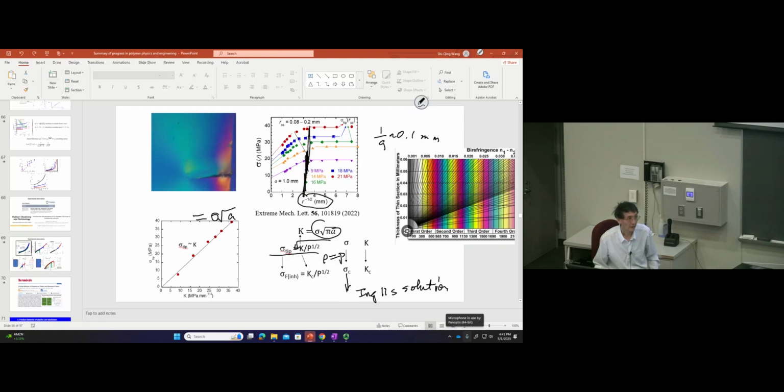Get it? So with rubbers, you find this cutoff to be, let's say, 50 microns or even 30 microns, but still you can resolve it without even struggling too much, because with a microscope 10 micron is generally the limit. So you have a window to show this stress will saturate.